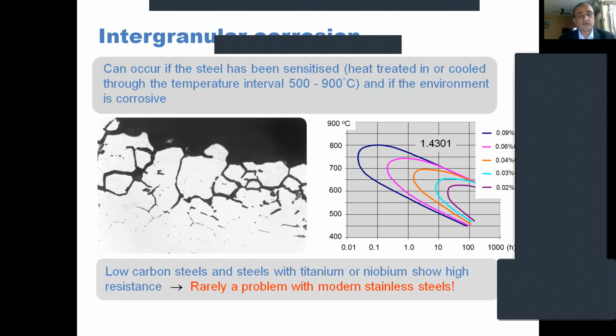Then there is another form, intergranular corrosion. It can occur if the steel is heat treated between temperatures of 500 to 900 degrees C, as a consequence of the precipitation of chromium carbide or intermetallic phases. This is where you can see the grain boundaries. Corrosion occurs here at the grain boundaries. Low carbon steel or steel with titanium and niobium shows high resistance, and it is rarely a problem with modern stainless steel.